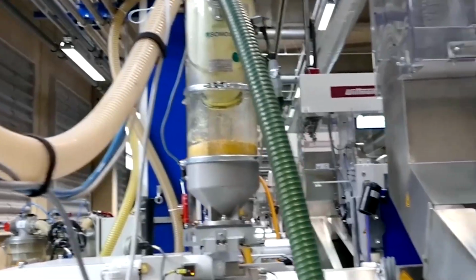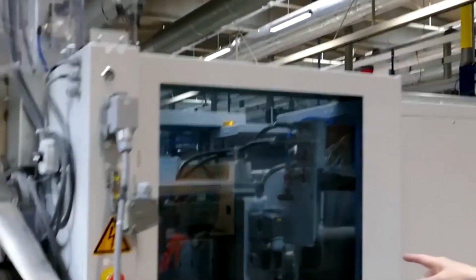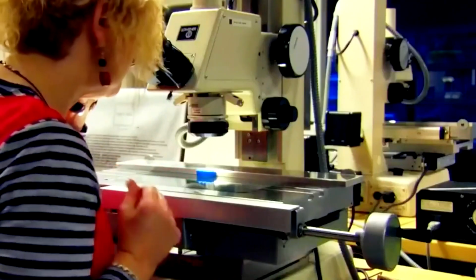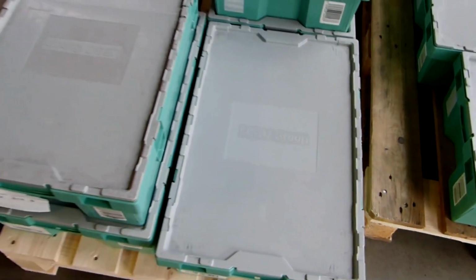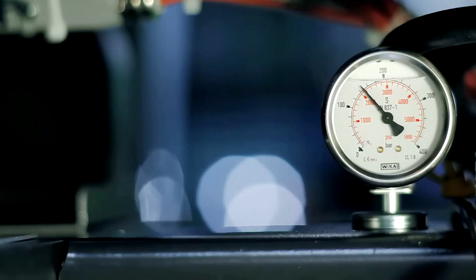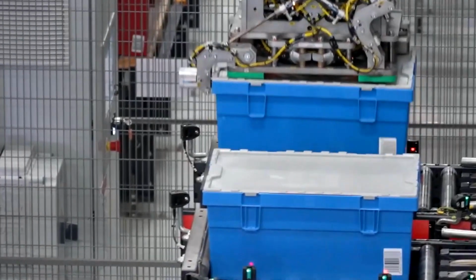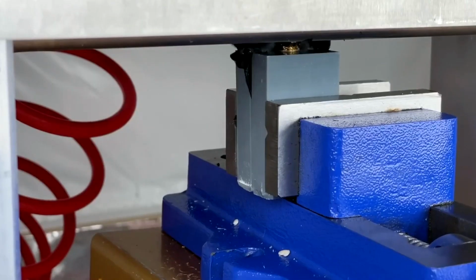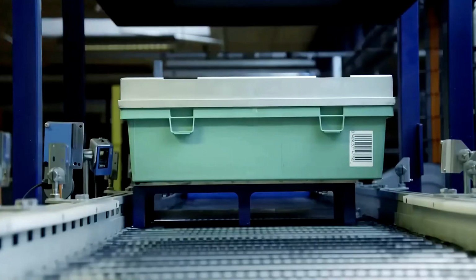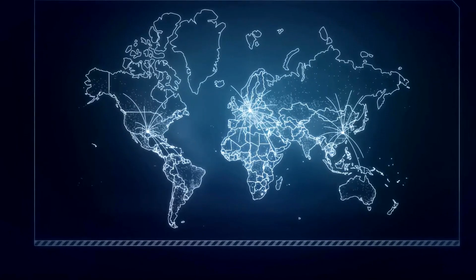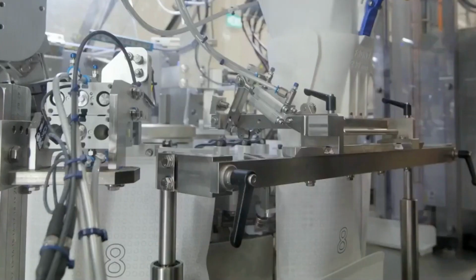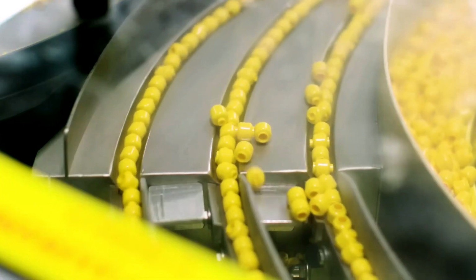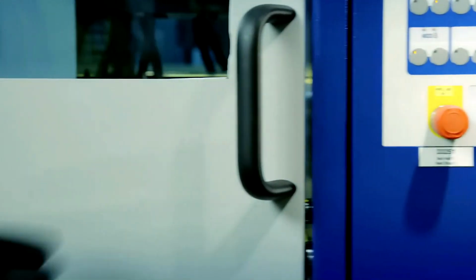440 to 590 degrees Fahrenheit is the thermal range required to transform solid plastic into a workable molten state. Why must the temperature be maintained within such a narrow window? The semi-processed material flows directly from the color blending stage into the injection molding area, which serves as the central hub of the entire facility. Any fluctuation in heat would compromise the toothpaste-like consistency of the melt, preventing it from behaving correctly under the immense forces of the machinery. The injection process occurs under extreme pressure.